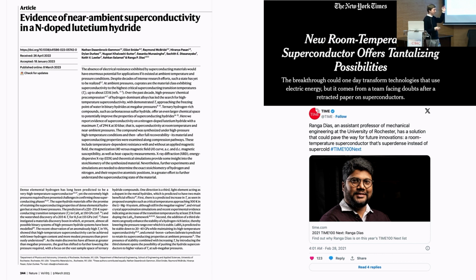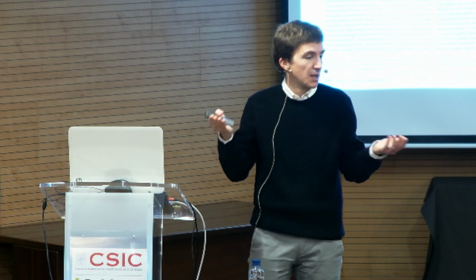So this comes from the group of Ranga Dias, who is, I don't know whether it still is, an assistant professor at Rochester University in New York, who before had also another very controversial paper claiming that he found superconductivity in a carbon-sulfur-hydrogen compound at also room temperature, but very high pressure. It was 300 GPa or 250 GPa. So that was not so unexpected. We had already 250 Kelvin superconductors at high pressure, 250 to 180.